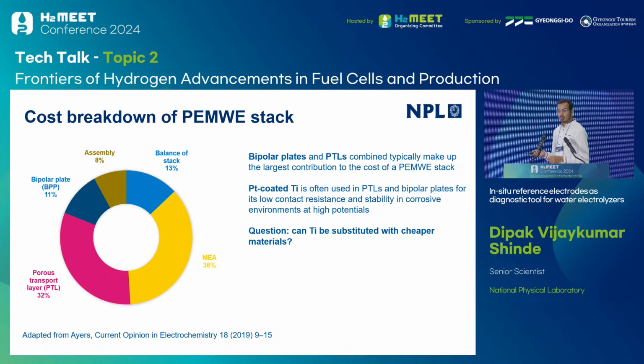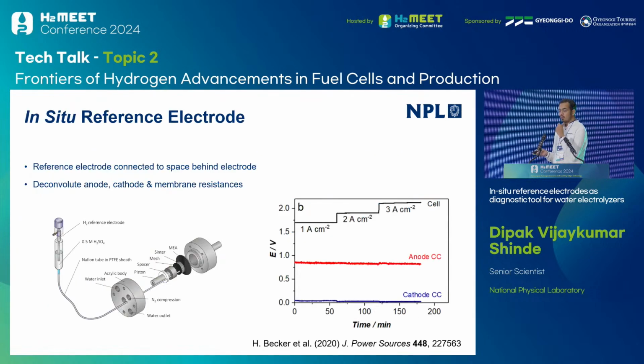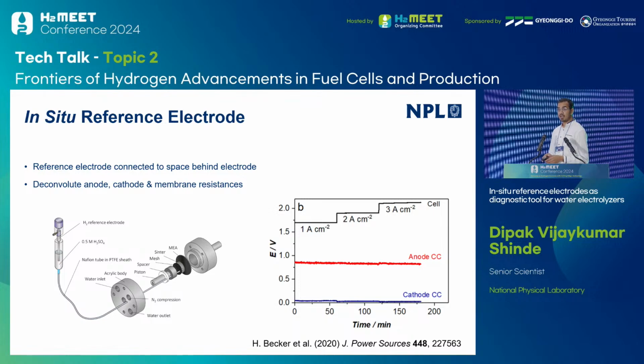Well, we prove otherwise. So what we did, we put a reference electrode probe near the current collector. So this is a typical lab scale proton exchange membrane cell. And with this probe, we show that the current collector does not experience the corrosive conditions. It stays at its open circuit potential, so it does not experience corrosive potentials. And therefore, you can replace your current collector with cheaper materials, maybe stainless steel.